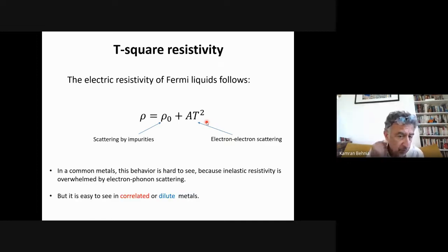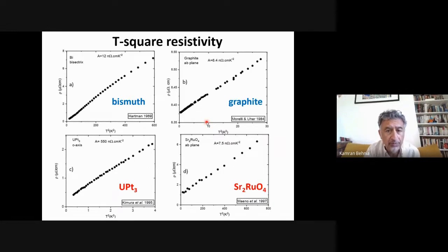On the other hand, if you want to see it in a correlated metal, like a heavy fermion system, or a dilute metal, like bismuth or graphite, actually it is easy to observe. It is much stronger than the electron-phonon term. So here I am showing you four plots obtained by different people, not at all our group, during the last decades. Here is the result for bismuth, a beautiful work by Hartman in 1969. Resistivity as a function of T squared is almost a straight line. The numbers are in micro-ohm centimeter. Here is T squared, so you can see that you have T-squared behavior. The slope maybe is changing a little. The same is true for graphite, obtained by Uher and his collaborator. You can see that the scale where T-squared behavior can be seen is much more limited.